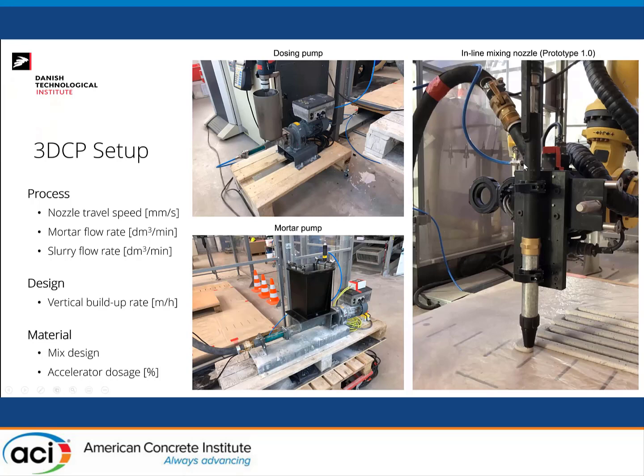And the reason for having a retarder and then an accelerator is that when we mix, we are doing batch mixing. So I mix like 90 liters of mortar, and I want that mortar to be as fresh as possible for the course of an hour or more, depending on what I'm printing. So I want to have a sleeping mortar, which only wakes up when it hits the nozzle. Everything before it should be sleeping, or in its dormant period the whole time.